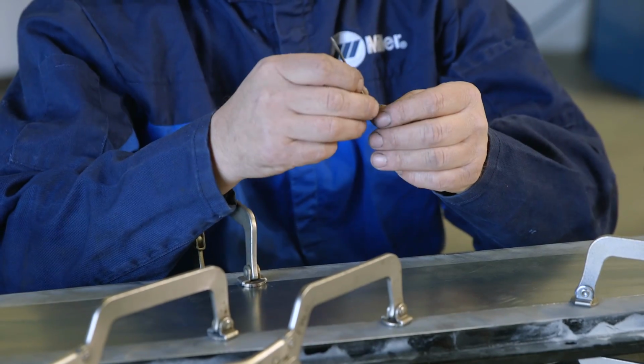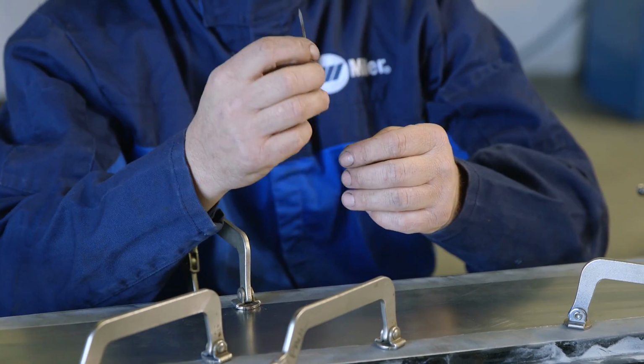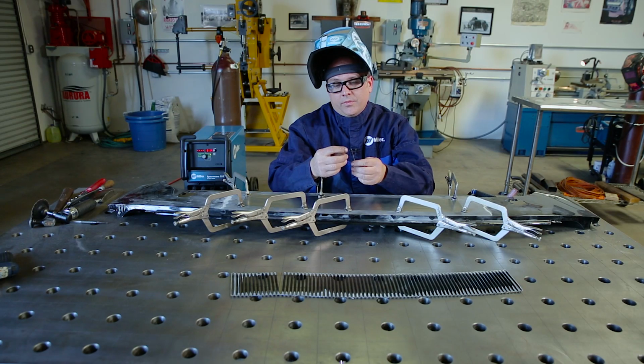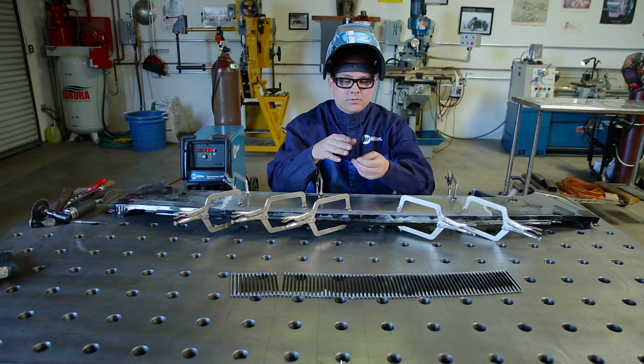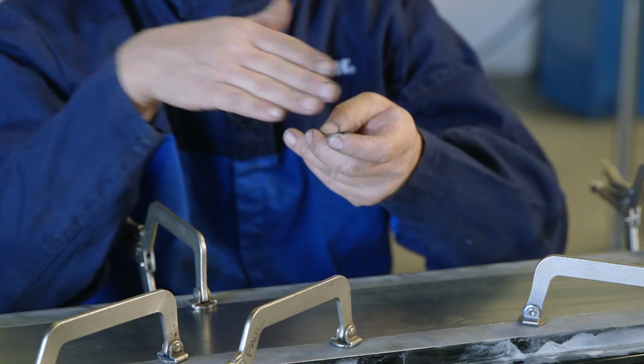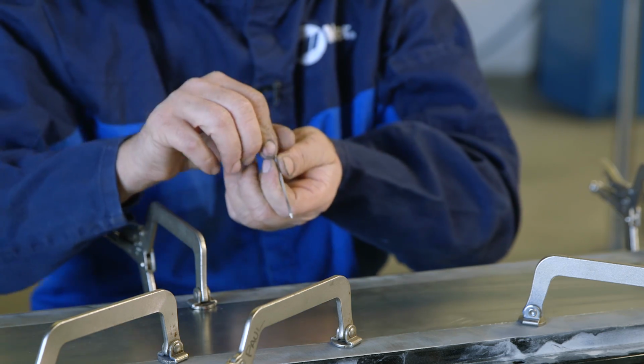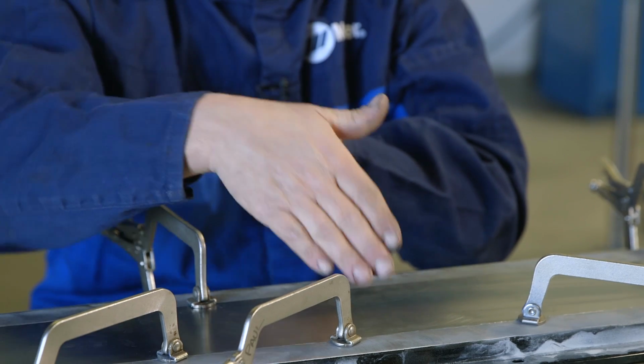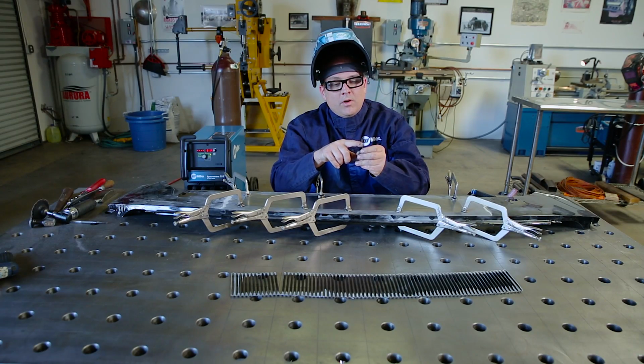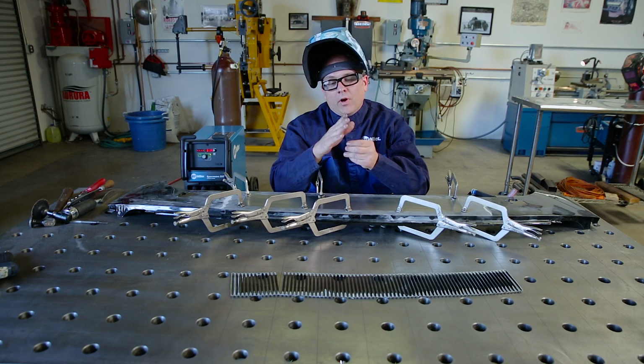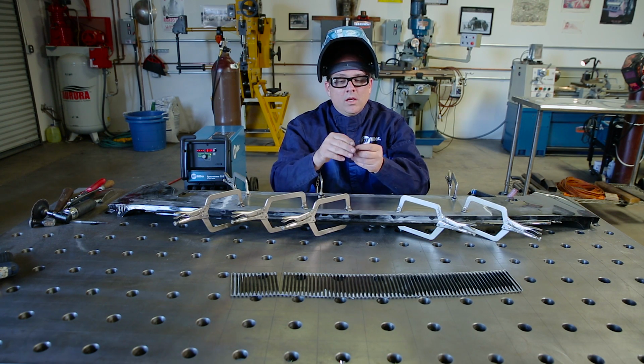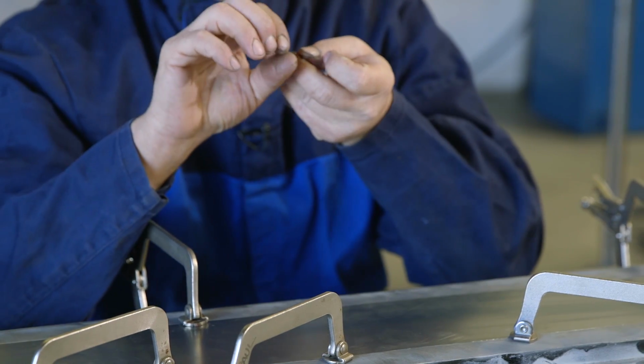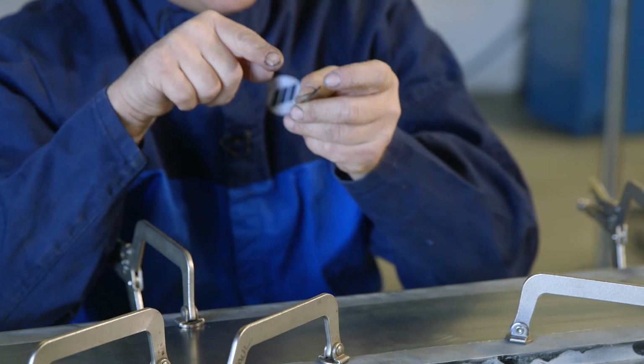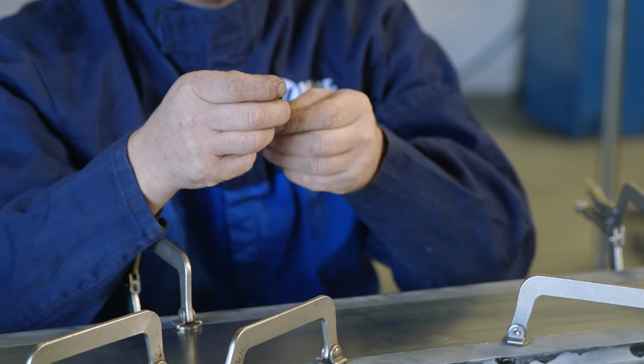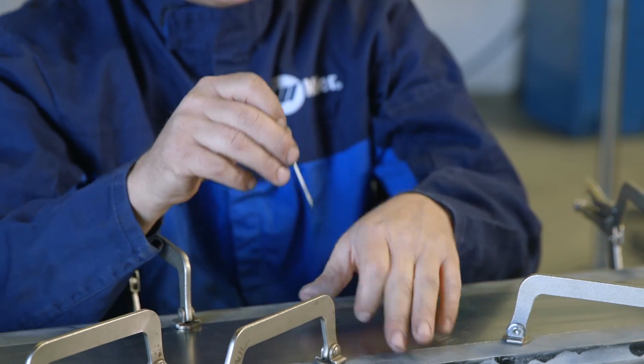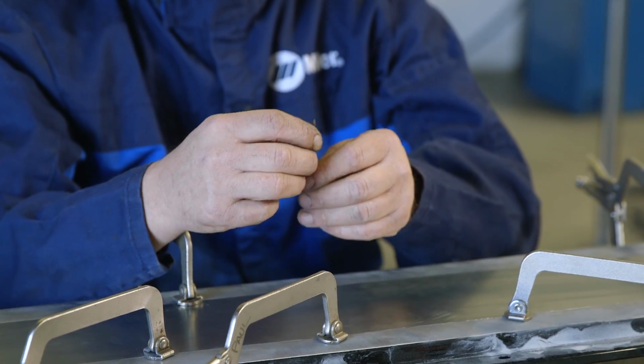One thing when doing light sheet metal is sharpening your tungsten properly. When you grind a tungsten, it should be ground towards the tip. So when you go into your wheel, you want it grinding away from the tip. But also there's all the little marks in it from the grain of the stone as it's grinding it. The electrons actually follow those lines so that it puts a nice sharp point to your arc, which really helps, especially on thin sheet metal. So now we'll start tacking.